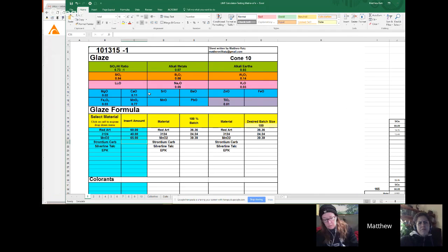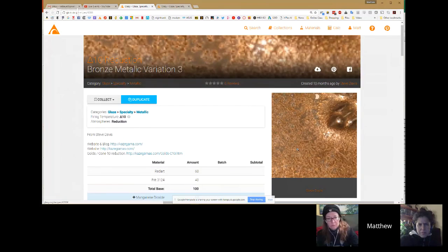Okay. So it's a totally out of whack recipe, but, the resolution on this sucks, you can see you're getting crystallization and phase separation. And we're not even at a 5 to 1. It's at a 6.7 to 1, but it's all about using manganese and being in that lower corner of Stull to get this crazy, crazy recipe. But all the trends are there. It's just using manganese as an RO.